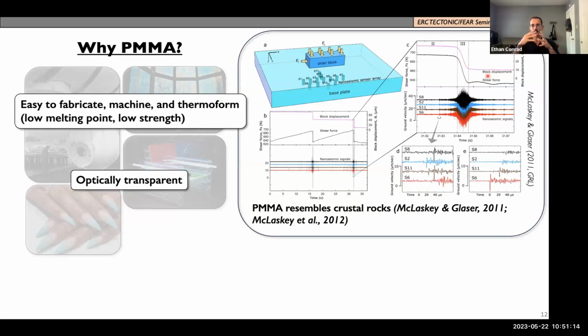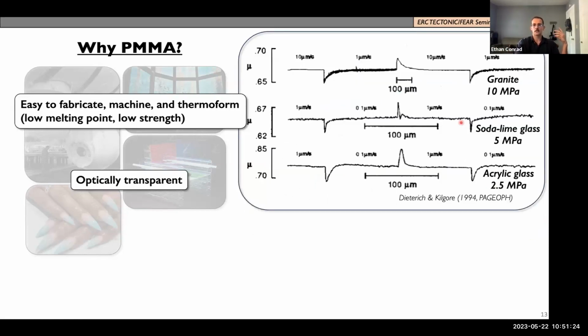Here's an example from McLaskey and Glaser, 2011. They found that PMMA strongly resembles crustal rocks, including its acoustic emissions and how the strength evolves. And this goes back to Dieterich and Kilgore, where they experimented with a variety of materials: granite, soda-lime glass, and acrylic glass. In this rate and state sense, where they're changing the slip velocities, you can see that the frictional evolution in acrylic glass strongly resembles that of granite, and it behaves very similarly to granite as far as how the strength evolves.